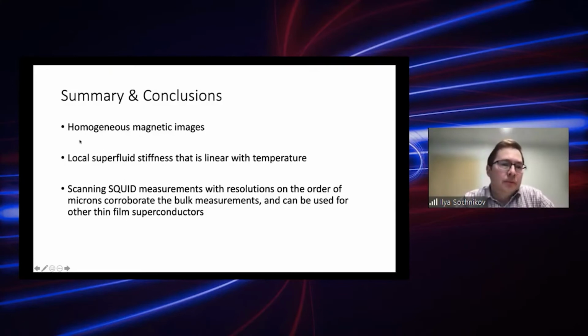Just to conclude, the samples were found to be quite homogeneous, and I was actually quite surprised to see that the landscape was quite homogeneous across the samples. Really, only variations beyond a few percent were coming from scratches created by us, rather than anything happening in the samples intrinsically. This is, of course, happening on the micron scale, which is the relevant scale for the penetration depth.